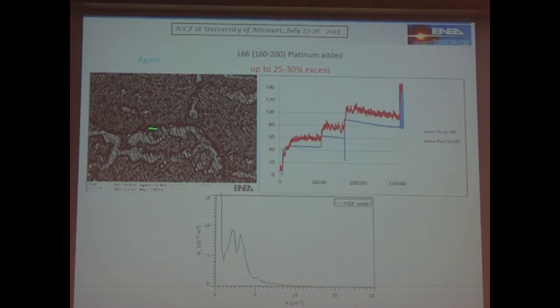And here, this is a cathode which was produced by ENEA, in order to come as close as possible to 64. So what they have done, they have doped the palladium with platinum and then etched it, and as you see, this labyrinth structure, and you see these two peaks. Although lower than 64, this experiment still generated excess heat of 25 to 30%.